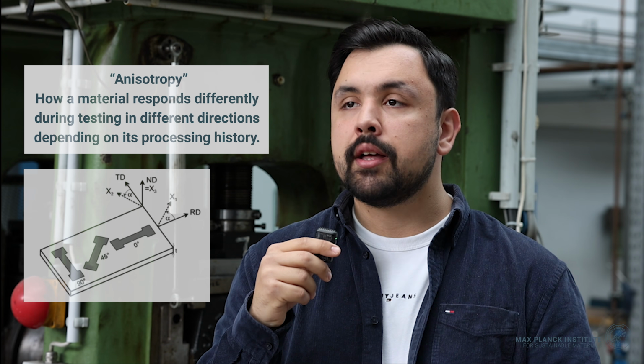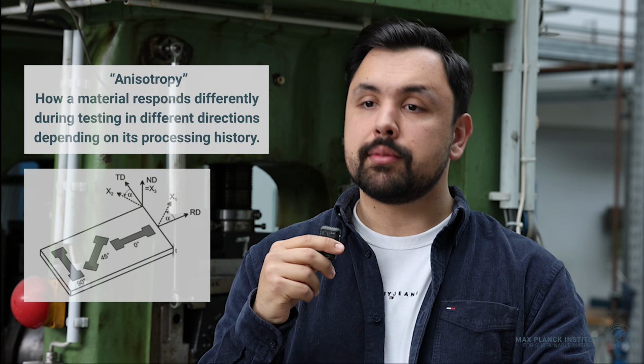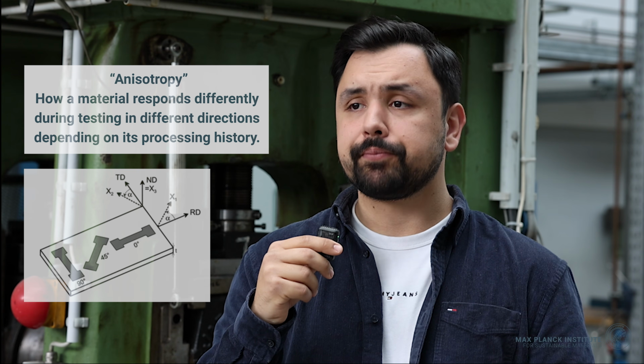Texture means that the crystals inside the metal orient themselves in particular directions during processing, and this orientation affects the properties we mentioned before. More importantly, how we shape a texture also affects what we call anisotropy, and then the properties we mentioned before change with respect to direction.